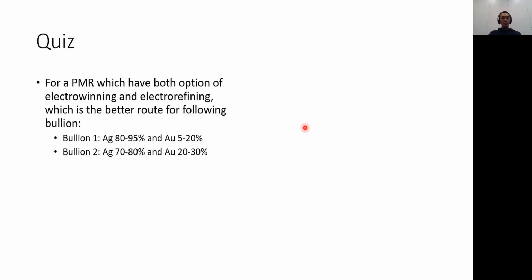And next, after we go through the silver process, another quiz to put that knowledge into application. I hope you guys will remember this course, and I will share these slides, of course. So for a PMR, which has both options of electrowinning and electrorefining, in electrorefining the silver is cast into silver anodes and then processed through electrorefining. And electrowinning is where the silver bullion is dissolved first and then put into electrowinning. So which is the best case for these two types of bullion? The first bullion has a silver content of 80 to 95, and the second one has a lower silver content and higher gold content.